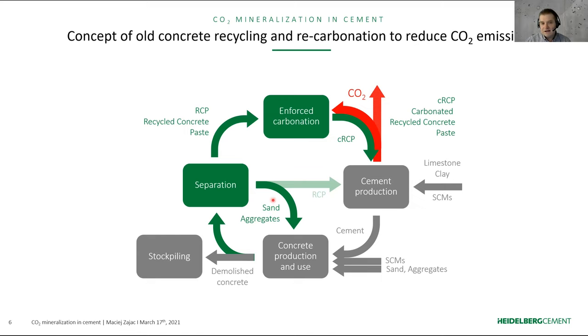Of course, the recycled sand and aggregates, provided that they are of high quality, can be used for concrete production, saving virgin materials. Now, the RCP, recycled concrete paste, can be used for enforced carbonation, so CO2 mineralization with the help of RCP. And then we find that this carbonated recycled concrete paste can be used for the production of new cement as a new supplementary cementitious material. Now I am leading projects whose target is to better understand enforced carbonation and the properties of the cement with this new SCM. I would like to share my experience on the next slides.